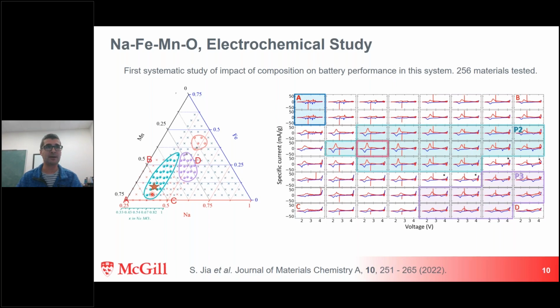And that was it. And we were able to find in a very short period that there's actually a large solid solution. There's a big region here. We can change the iron content very, very significantly. And we can change the sodium content. So there's a lot to play on. It's not just one composition and we're done. So this is really important to realize that there's a lot of region to screen. And then we found two other phases, and the stars here mark the ones that were in the literature before. So there was one of each of these, and we found again a large region.